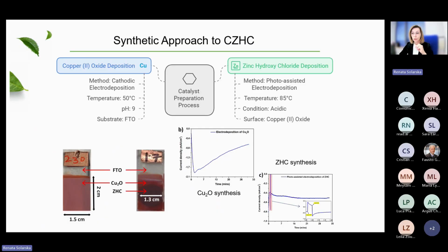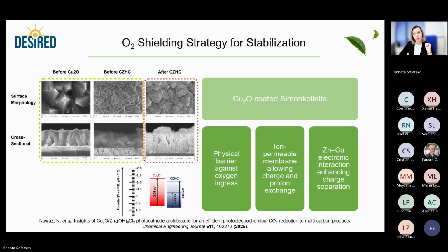we engineered an electrode where the deposition of the zinc hydroxychloride is on the surface, but at the same time affects the properties of the bulk. So based on the electrode deposition process, we produce the copper 1 oxide electrodes, and then by photo-assisted deposition, the zinc hydroxychloride has been deposited on the top. In that way, we engineered a contact between the copper 1 oxide and the zinc hydroxychloride.